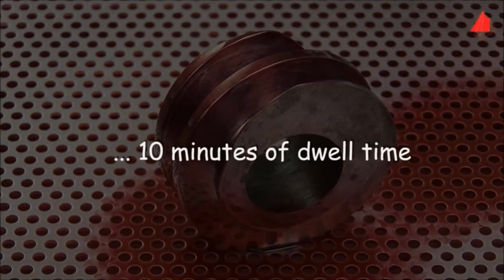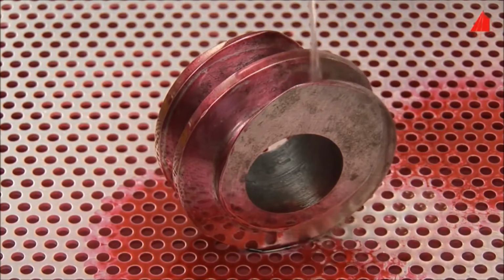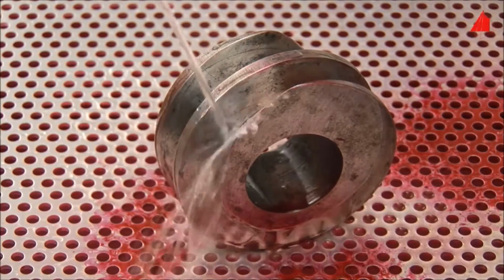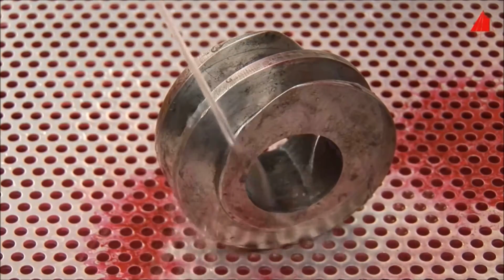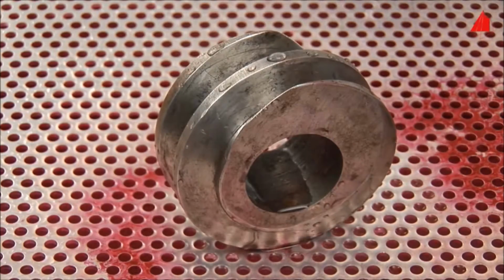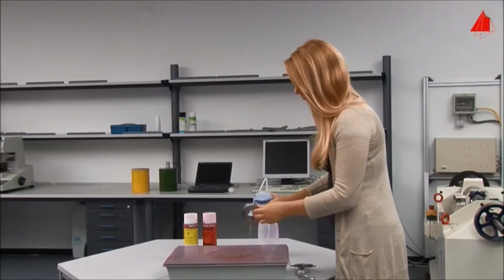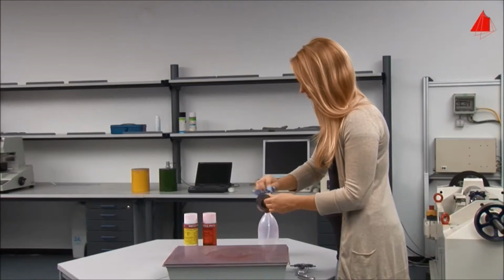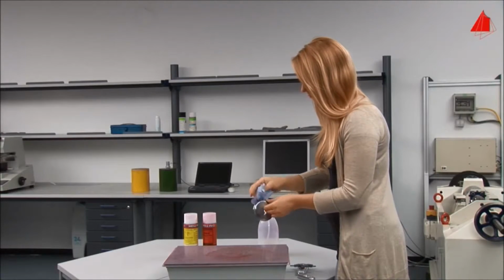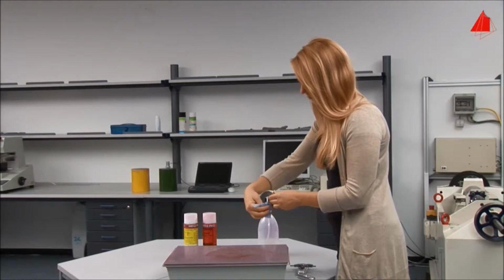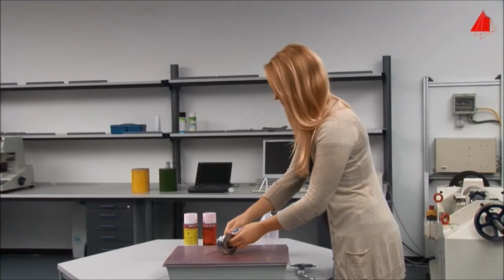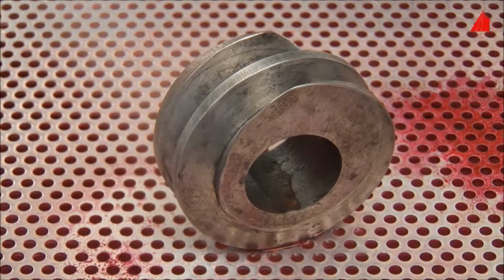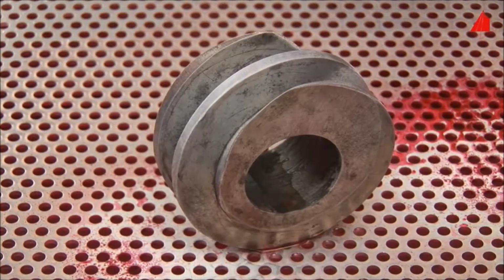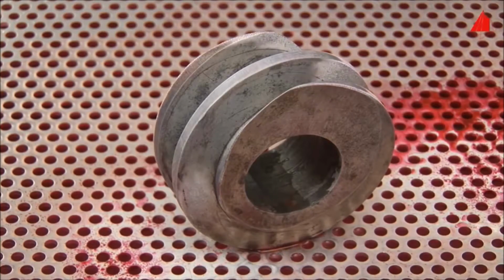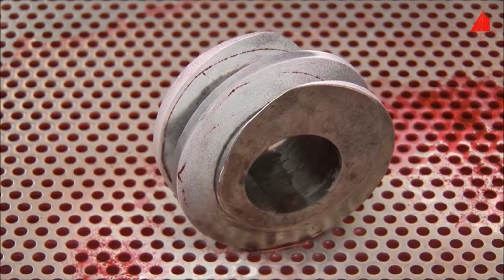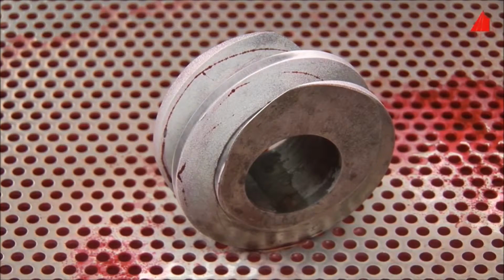After a dwell time of about 10 minutes, she removes the excess penetrant from the surface by rinsing the test piece gently with water. She takes care not to rinse for an unnecessarily long time because the penetrant is supposed to stay in the defects. Now she dries the surface of the sample with a cloth to absorb the excess water. As the final step, she applies the developer and lets it dry. That's it. Several cracks are indicated on the surface in deep red color.